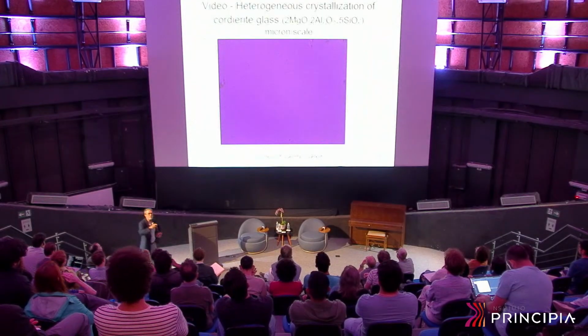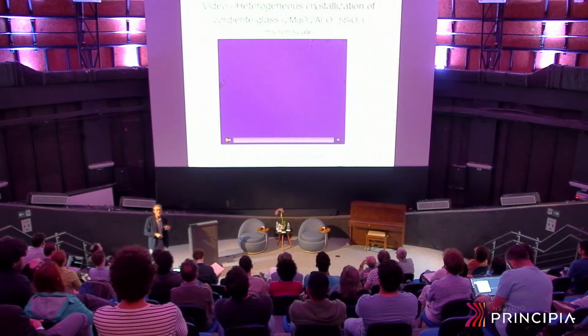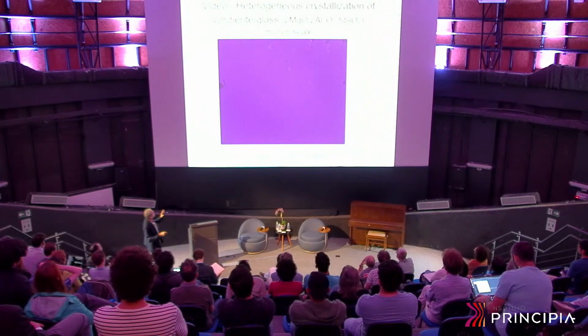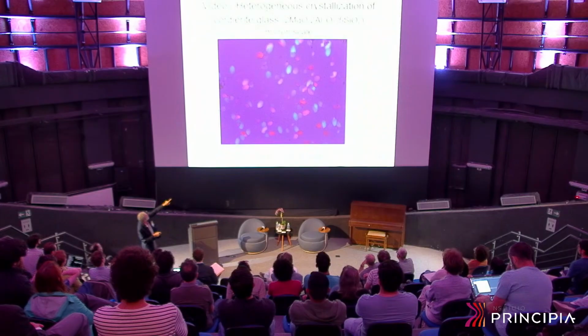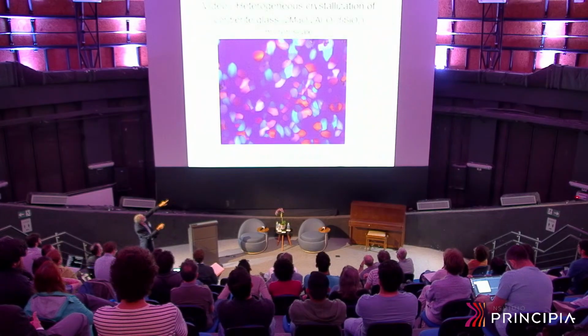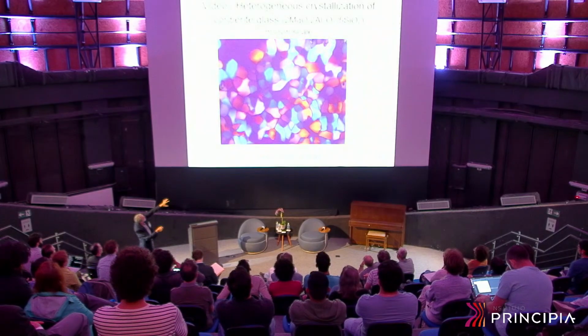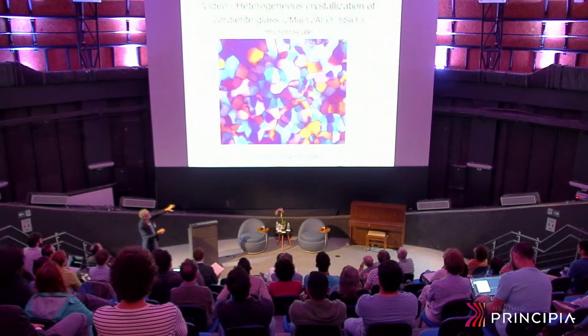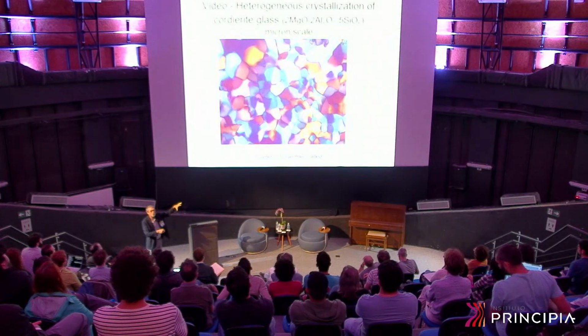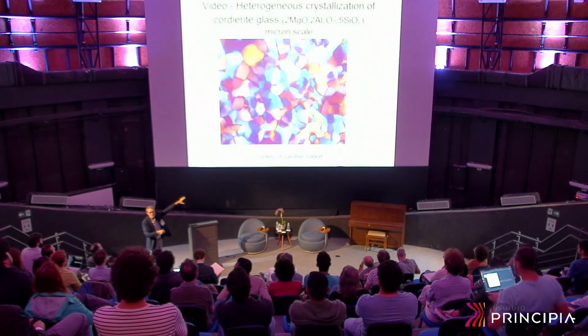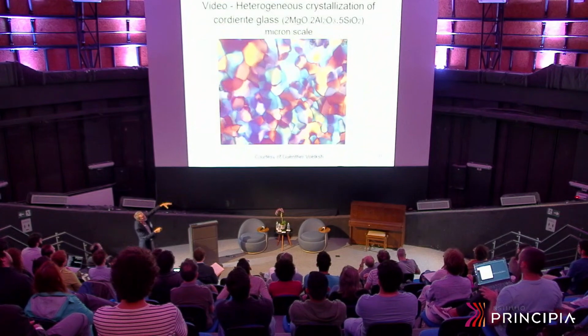Let's see another video, please, of a real crystallization. This is not MD, this is real crystallization of a particular glass-forming material. See? These crystals formed very fast, and then they started to grow. This is the final microstructure. This is a magnesium aluminum silicate, a glass-forming material.